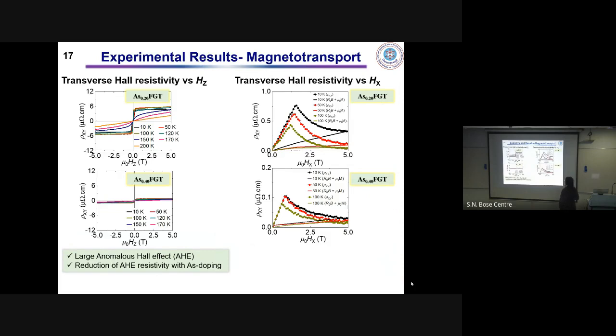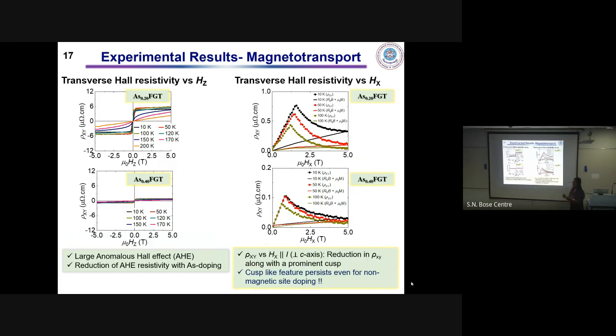And moving on to the magnetic transport result, here also we have observed from the transverse Hall resistivity versus magnetic field along the Z direction, in both the samples a feature of the anomalous Hall effect. However, the magnitude of the anomalous Hall resistivity decreases with increasing arsenic doping. And when we measured the transverse Hall resistivity as a function of magnetic field applied in the plane of the sample, we could see the same behavior of topological Hall effect, or unconventional Hall effect, in both the systems. And we tried to separate out the contributions from ordinary Hall effect and anomalous Hall effect, just like the cobalt doped samples. Here also we can clearly see a significant additional contribution to the transverse Hall resistivity. So we confirm that this skyrmion-like feature persists even for non-magnetic site doping.